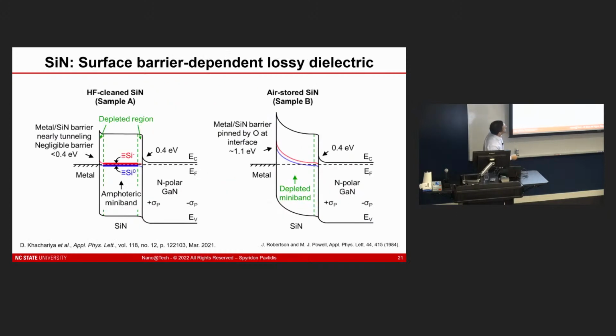So what did we conclude from this? I'll just briefly mention this. This was an interesting interpretation where we sat down, and there are other results in this paper as well where we did XPS and other techniques. But basically, we were able to understand that depending on what the surface termination is and how you treat that surface, the dominant barrier will either be at the surface, which is this oxygen-terminated case where you have a large barrier here at the surface, or that surface barrier will be quite small and the dominant barrier will be at that interface below there where the silicon nitride and GaN is.